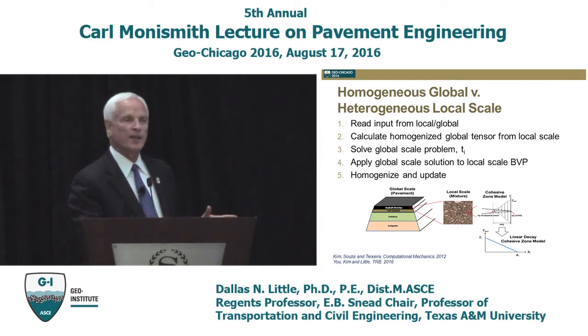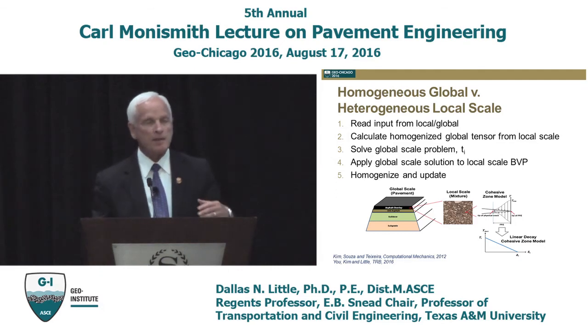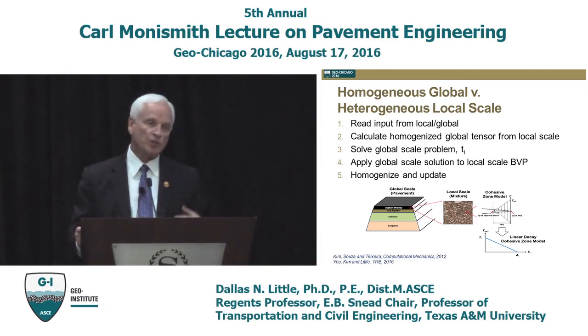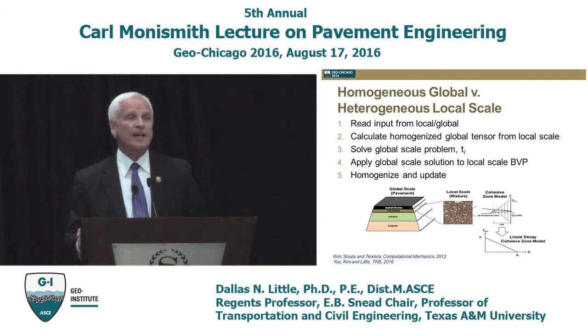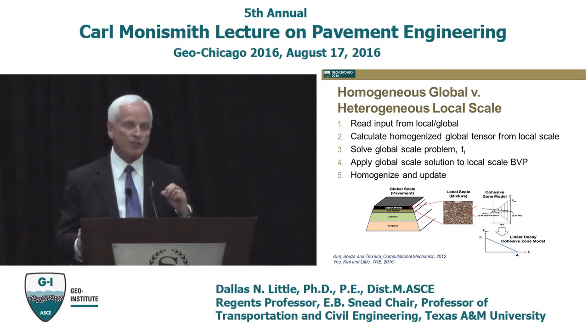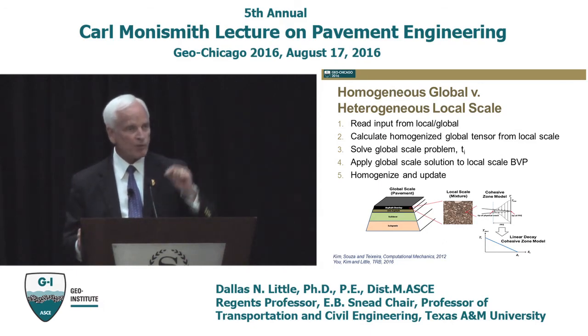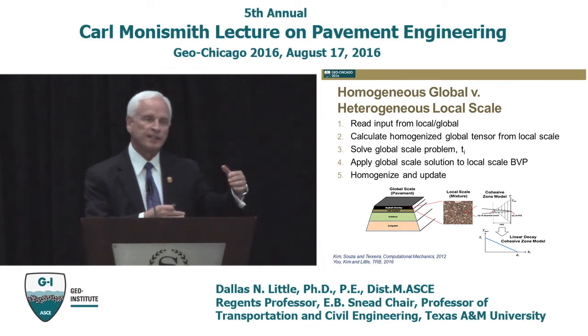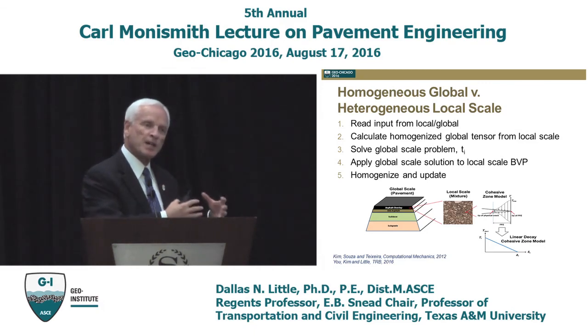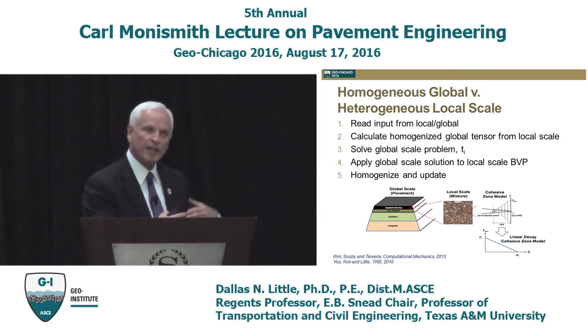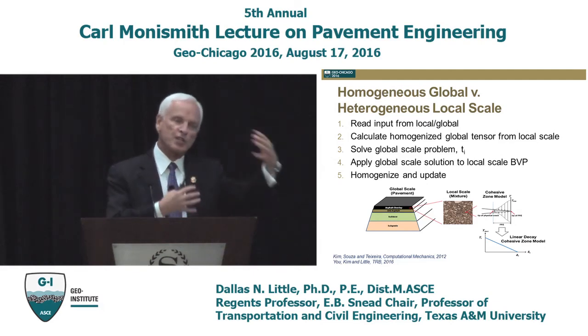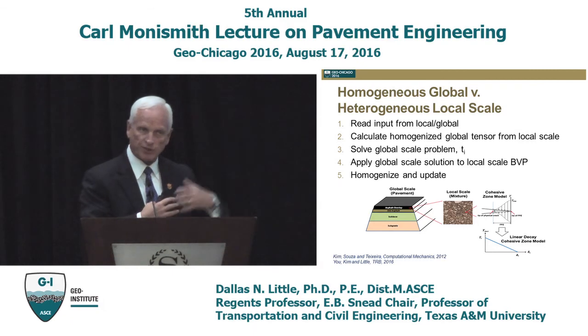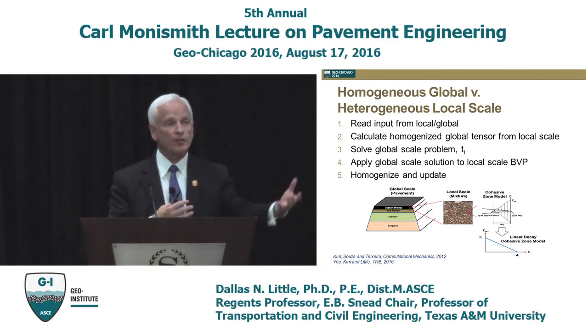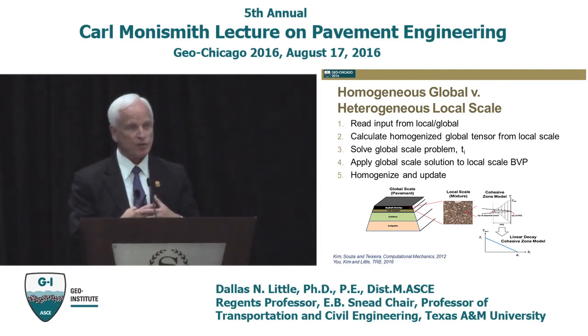And that allows him to virtually work at the mixture scale by changing properties of the mastic, by changing properties of maybe the aggregate distribution, changing certain details of the mixture, and not being limited by laboratory tests, but to actually see how that will affect the pavement because we're communicating back and forth. The main point of communication there is going to be when the mixture becomes damaged because of some weakness in the composition of the mix, how does that play at the global scale? Because you're going to transmit that information, that stiffness information, for example, to the global scale. At the global scale, you're going to have different stress states that are going to be communicated back to the mixture scale.